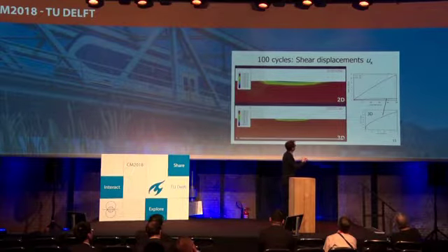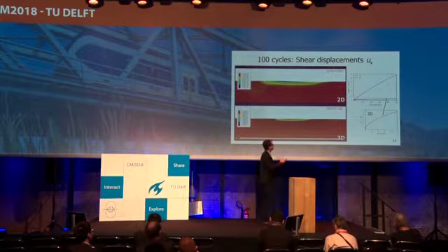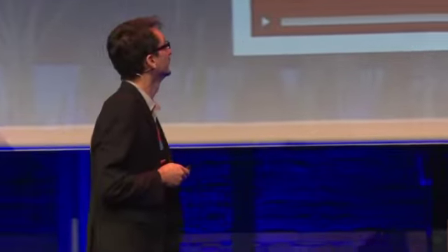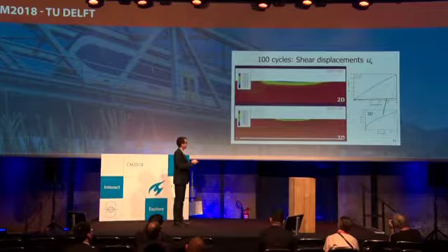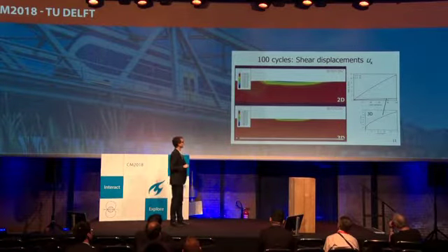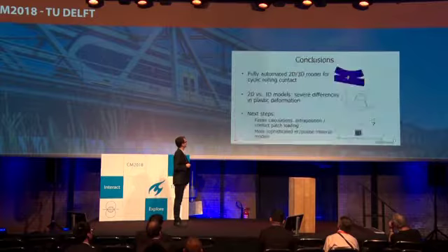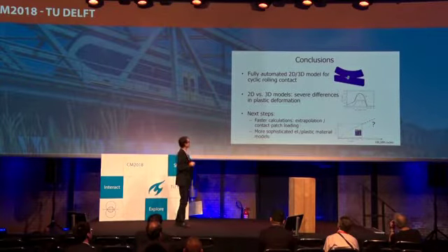And when we look at the diagram over the 100 cycles that we used here, we see that that's more than an order of magnitude. I didn't mention this in the beginning, but of course, in the rail, or in this test rig, we have a very long rolling length. But in the model, to keep it efficient, we should take a rolling length which is as small as possible, because double the rolling length is double the calculation times. Yes, that was what I wanted to say, basically.